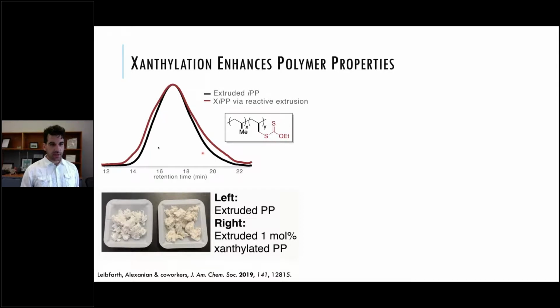And you can see again here, this is one of these size exclusion chromatograms. So, you may see in polypropylene a little bit of an increase in these lower molecular weight fractions. But we actually did this experiment with just one of those traditional peroxide radicals. You see this whole peak shift down here. So that is obviously not happening with our material. And this was really a huge advance in the field.